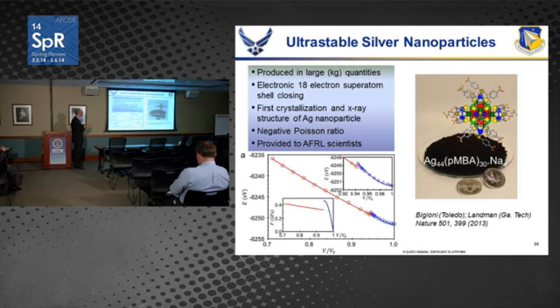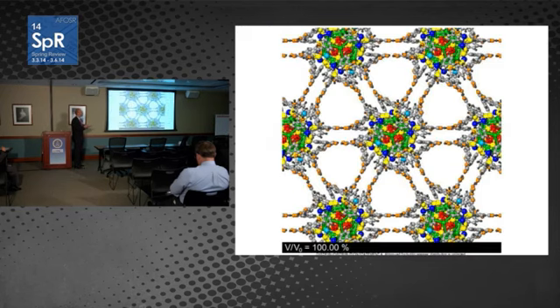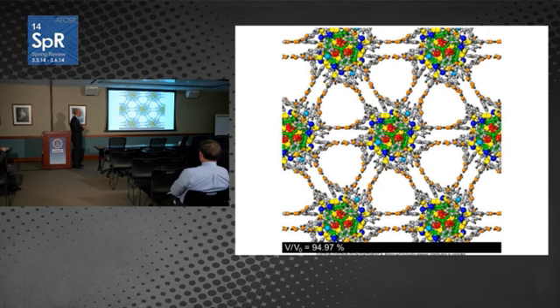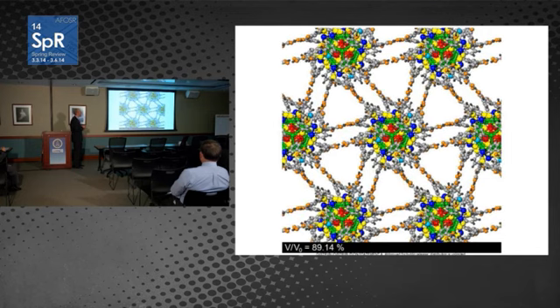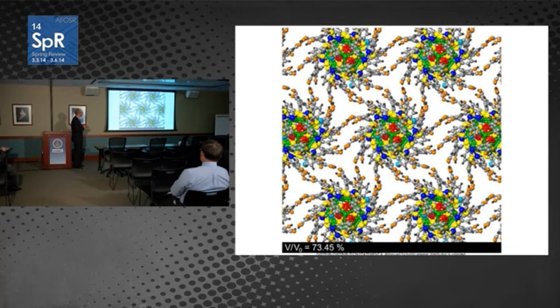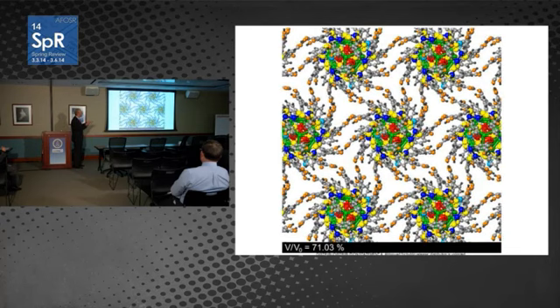You can compress it to a particular compression, and then there's a drop over here, almost a phase transition, a change in properties. And you'll see what happens as we look at this crystal structure that we have from the simulation. As we begin to compress that, now each click is compressing this further and further, you see all of a sudden the lattice start to change. And these ligands that help form the lattice are buckling and providing an interesting energy dissipation mechanism. So it's an interesting mechanical property that's emerged from these lattices that we have from these nanostructures put together.